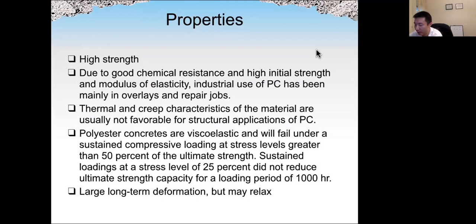The thermal and creep properties of these materials are not as good as traditional Portland cement concrete. Okay, it is susceptible to high temperature changes in performance, and also the creep is much higher. Because of that, we need to reduce the loading stress level to less than 50% of the ultimate strength. For sustained loading at a stress level of 25%, do not reduce the ultimate stress for a loading limit of 1,000 hours. So we need to reduce the requirement, considering the higher creep for this type of material. So it has larger long-term deformation, but it may relax, which could be a good thing because relaxation may cause stress redistribution of the reinforced concrete.